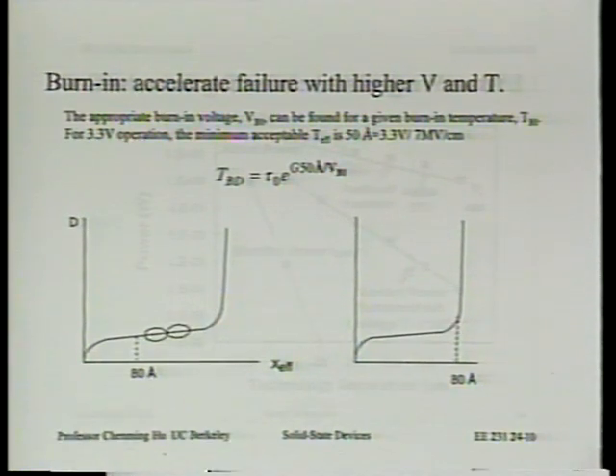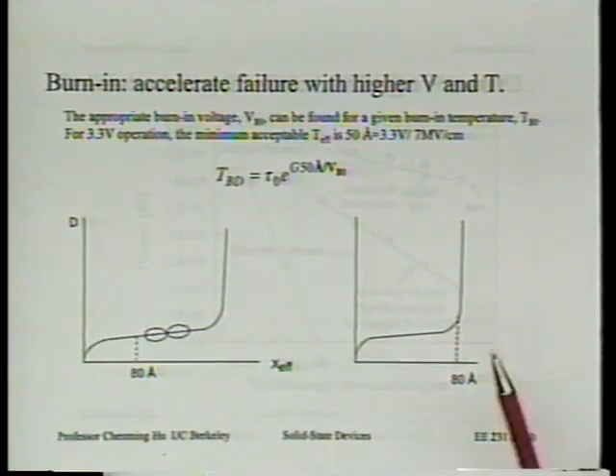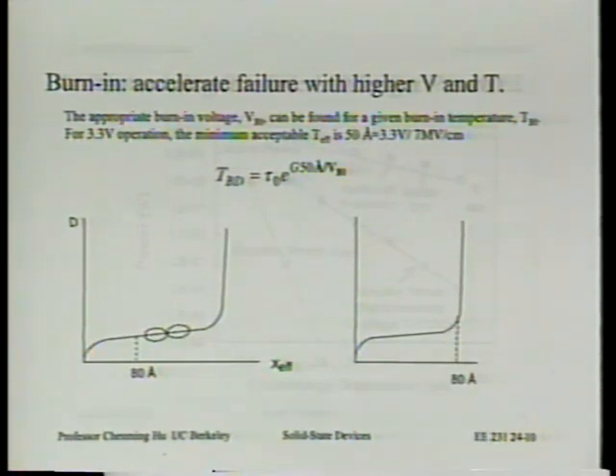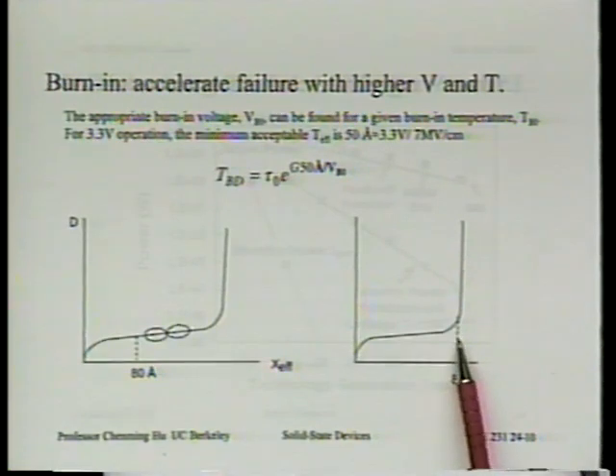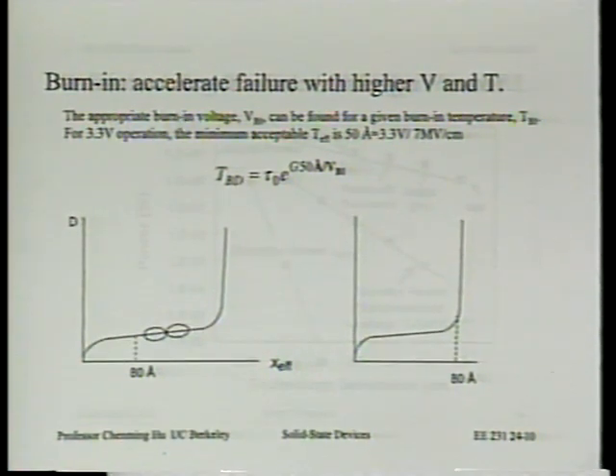A question: will the burn-in process introduce more defects? The answer depends on the shape of this curve. For example, if you design your nominal operation condition with very little margin left, some burn-in could push everything toward breakdown. But for older technology, the nominal operation condition typically has a large margin — the intrinsic lifetime is actually quite long.